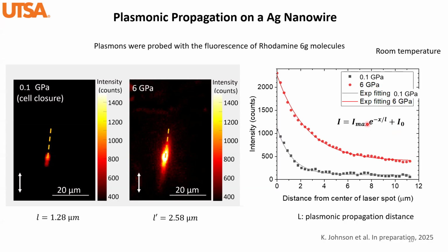On the left side, we have the ambient condition, when the cell was just closed under lower pressure, and the propagation distance is about 1.28 micrometers. On the right side, when the pressure was increased to 6 gigapascals, we see that the propagation distance doubled. This is really promising, but imagine we have dye molecules everywhere inside this cell. It is a really complicated system.